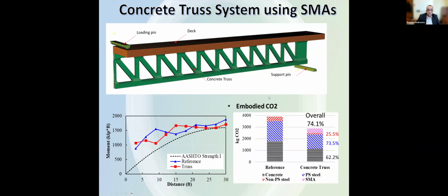The great finding was that we were able to achieve or meet the AASHTO strength limit states while still cutting the amount of material by over 25% and the embodied CO2 associated with the production of these materials. So there is potential there, no question about that, and we are now working on validating these results experimentally.